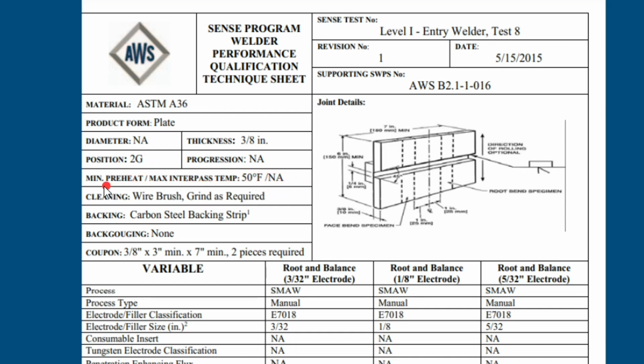It doesn't really have a minimum preheat, just 50 degrees. So unless you're keeping your metal outside, there really isn't a preheat, and no maximum interpass temperature. We can clean with a wire brush or grinder as required. Carbon steel backing strip. The coupon is going to be 3/8 inch thick, 3 inches minimum for each side,